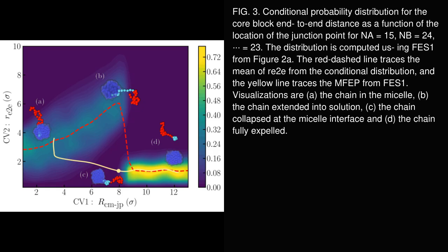The authors interpret this distribution as indicating that prior to fully escaping, a chain more likely adopts an extended conformation, stretching into the solvent. Near the transition state, the distribution becomes bimodal, reflecting coexistence of extended and collapsed states. This analysis supports previous findings where umbrella sampling showed growth of chain size, followed by collapse during escape, further elucidating the complex conformational changes chains undergo in this process.